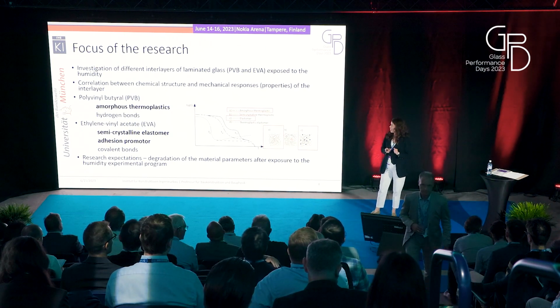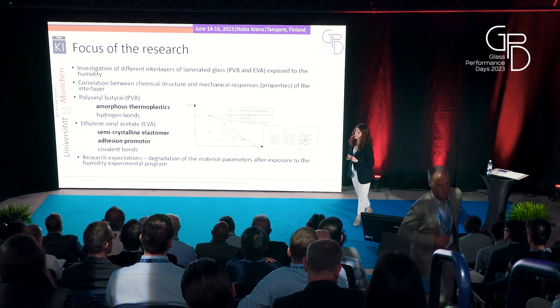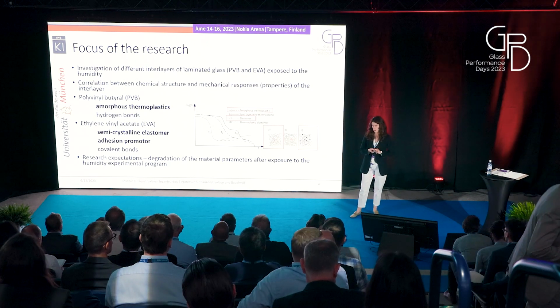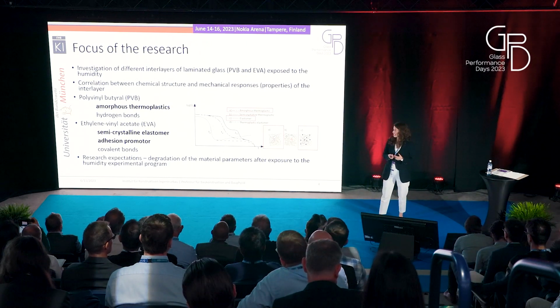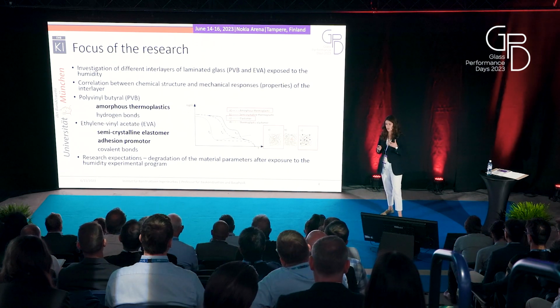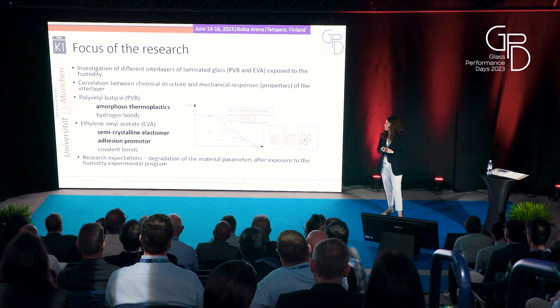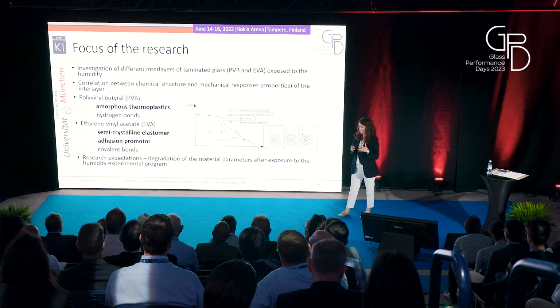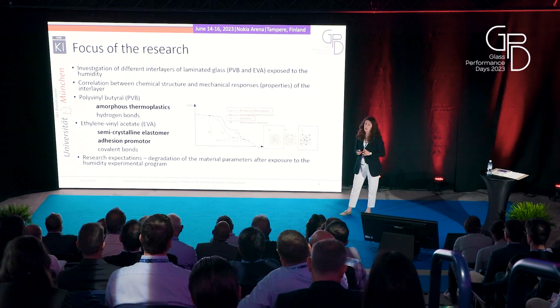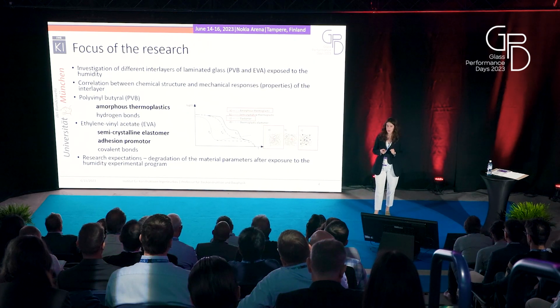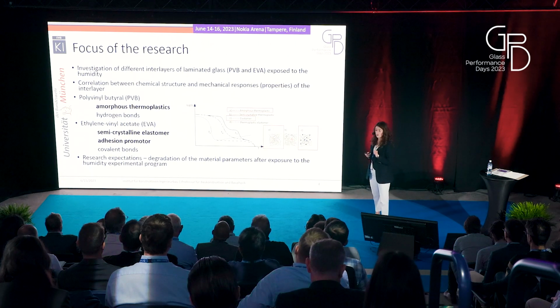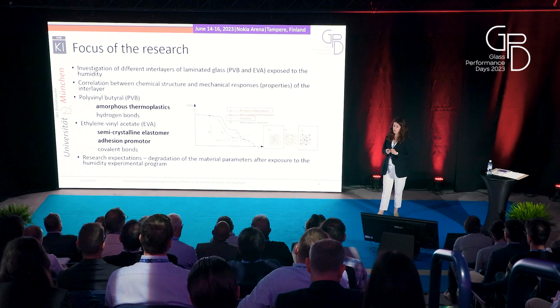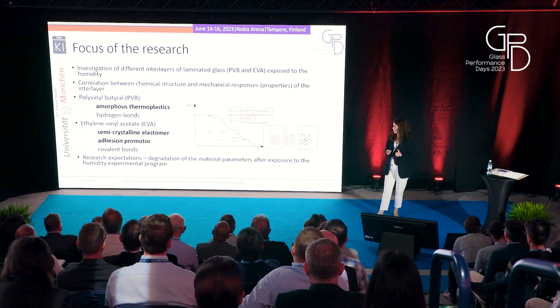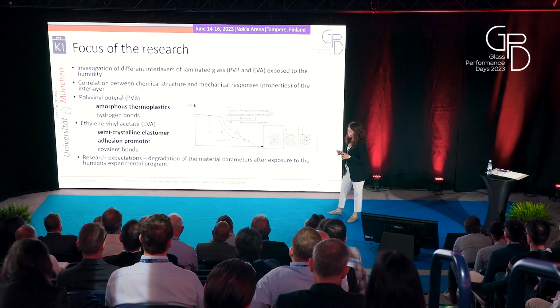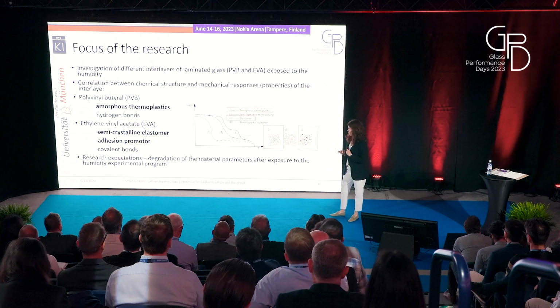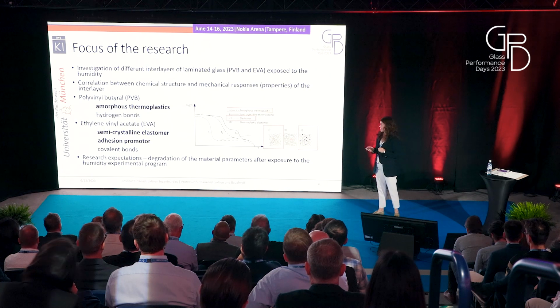That's in contrast to EVA, because EVA cannot react alone with the glass, which means that during the production process, certain adhesion promoters, certain sealants, so chemical compounds, are added to the EVA in order to create covalent bonds. Covalent bonds belong to strong chemical bonds. They cannot be easily broken just by adding water to the equation. We need to insert a huge amount of energy, or maybe some strong acid, in order to break them. So these are the two main differences between these two interlayers. There are others, but we don't have to go that deep into them.